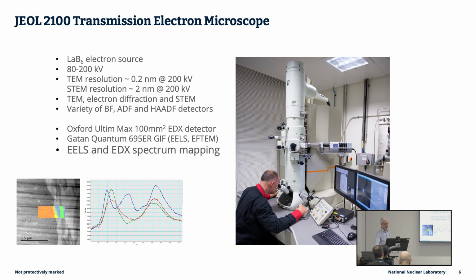The example at the bottom there shows some EELS studies of the oxide metal interface in oxidized zirconium, where each of the phases has a different signature in the EELS spectrum and allows you to map the phases present at the interface. This example was before we had the cryo stage, so unfortunately there's quite a lot of hydriding going on there, which is pure artifact.